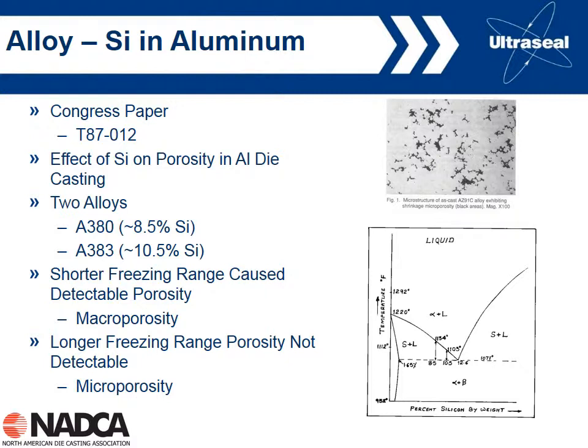And so this can be explained, again, by the width of the freezing zone, the width of the mushy zone we talked about previously. If you look at the aluminum silicon phase diagram in the bottom right here, this is the freezing range for the 383 alloy. It's pretty narrow, while the freezing range for the 380 alloy is much wider. We talked about this in the first webinar. Short freezing range alloys such as 383 tend to produce macro porosity, while wider freezing range alloys such as 380 tend to produce wider dispersed micro porosity, smaller porosity. So in both alloys we're going to get about the same amount of porosity, but we get smaller and wider distributed porosity in the 380. It's shown here on the top right.